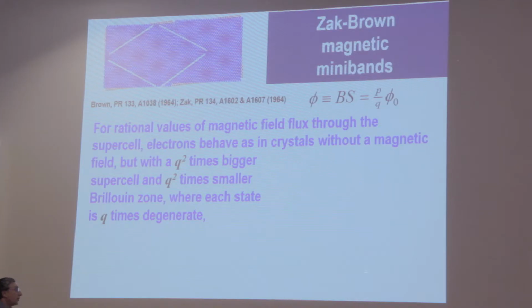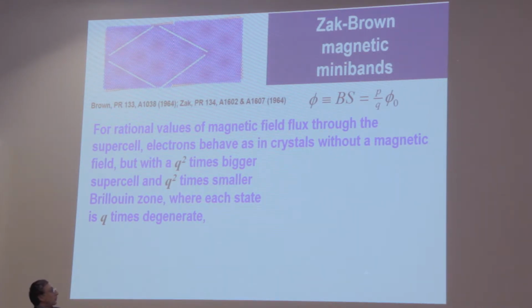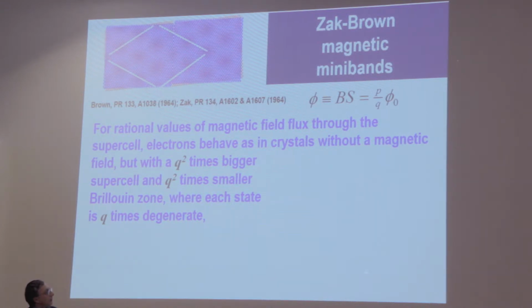So what it does, it produces the behavior of electrons that is exactly the same as in a usual crystal without any magnetic field, but this crystal would have q squared times bigger supercell. It would have q squared times smaller Brillouin zone as a result of that. And just by taking a view that the q squared is too big to make it rational, it's enough to multiply it by q, not by q squared, to realize that each of these states in the Brillouin zone will be also q times degenerate. And this is a nice result that one may keep in mind for the future, thinking about the physics of electrons in such magnetic minibands.